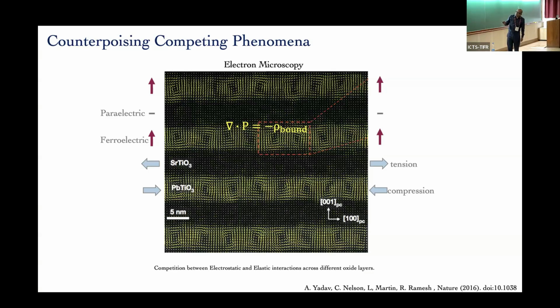Now at the interface, you have del dot P, the divergence of polarization, which is going to have a lot of bound charges here. Because suddenly you have polarization, then nothing. So obviously it's going to pile up a whole bunch of positive charges and negative charges, but they have nowhere to go. So the system is frustrated. Okay. So what does the system do as you grow it and cool down?